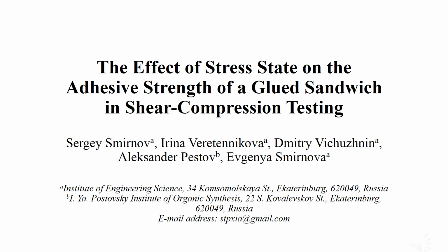We would like to present our research work, The Effect of Stress State on the Adhesive Strength of a Glue Sandwich in Shear-Compression Testing. Modified epoxy materials are fairly often used as coatings, substrates or interlayers. In this case, it is important to have a material with low susceptibility to long-term mechanical effects, including local ones, and to know the mode of failure.